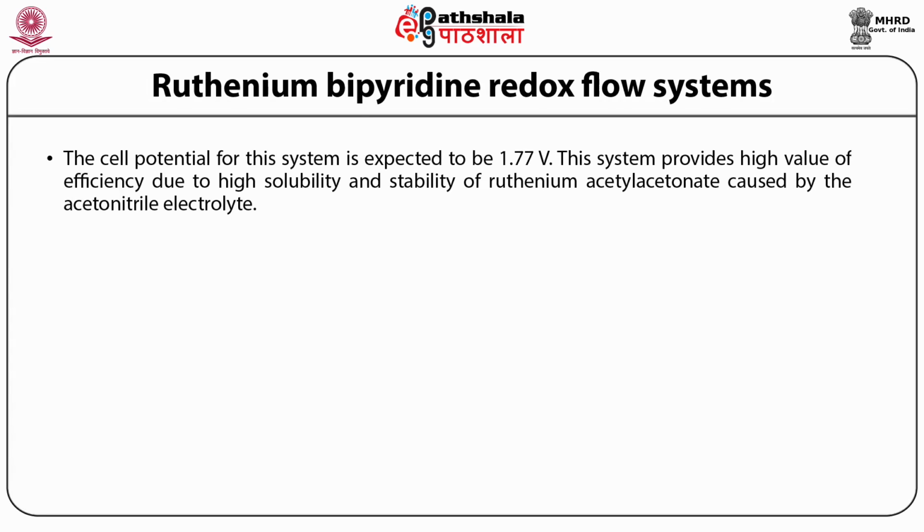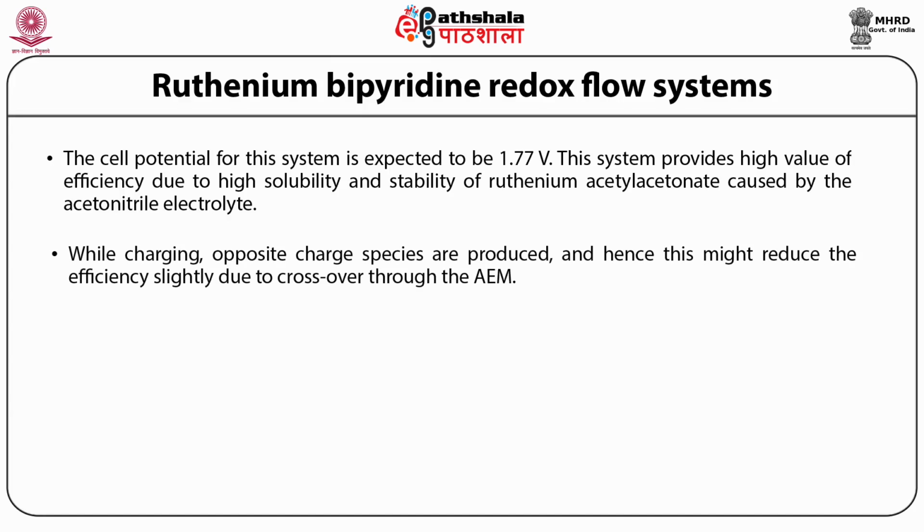This system provides a higher value of efficiency due to the high solubility and stability of ruthenium acetylacetonate in the acetonitrile electrolyte. While charging, oppositely charged species are produced, and hence this might reduce the efficiency slightly due to crossover through the AEM.